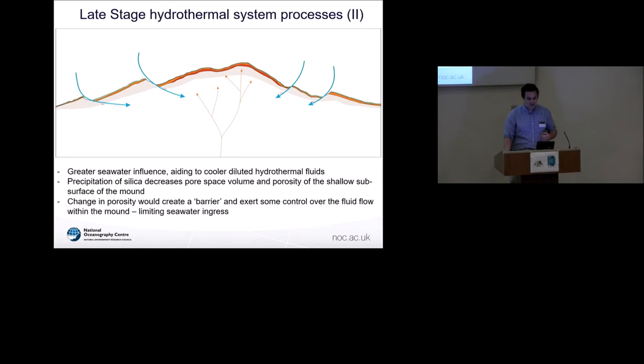Then we have the second process, which is discussing more of the silica precipitation. So silica is typically temperature controlled, so there has to be some kind of cooling involved. And then you have this silica depositing, and it's nucleating on the iron oxides, regardless of how they're formed. And we have this example where you're having this decrease in pore space, this decrease in porosity, and it could potentially be creating a barrier over the underlying massive sulfide units and preventing the oxygenated seawater from getting into the deposit itself and oxidizing the ore minerals themselves.